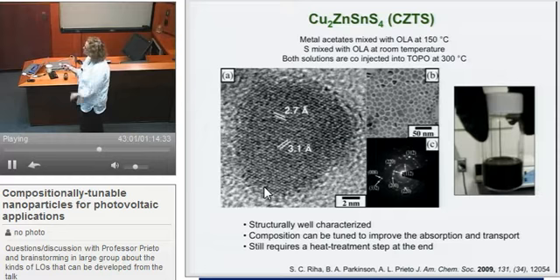In a separate vial, we mix elemental sulfur with oleylamine, and again, the idea is the oleylamine is going to reduce the sulfur to 2-. And then both of those solutions are co-injected into trioctylphosphine oxide at 300 degrees.